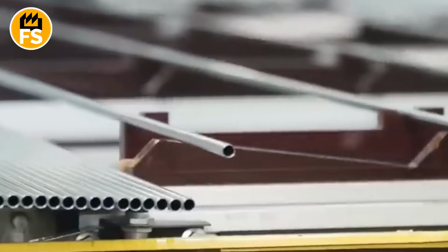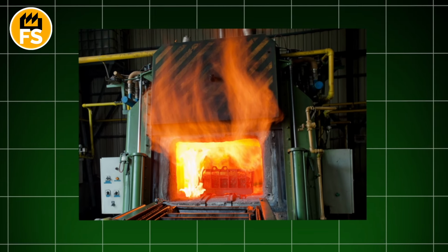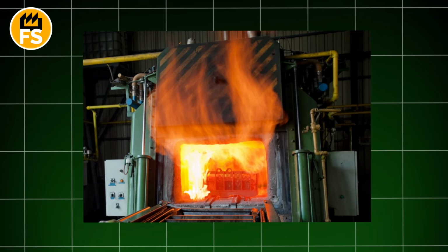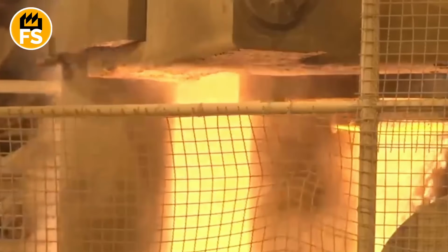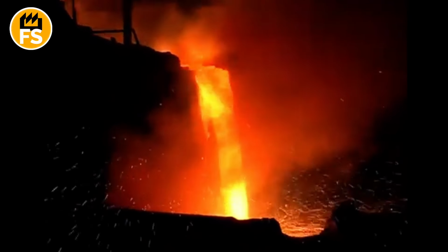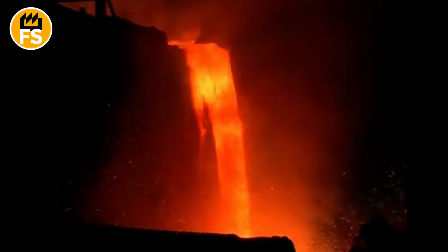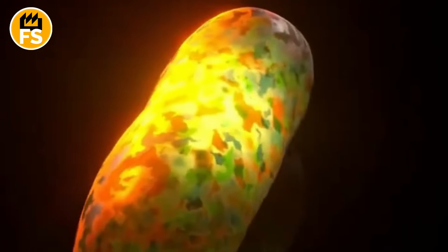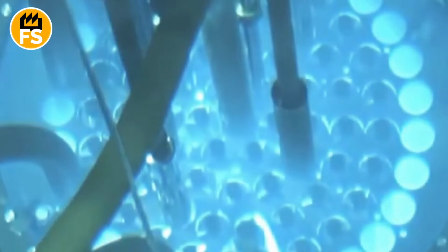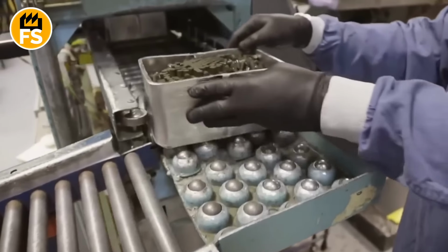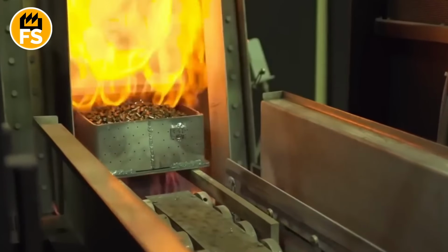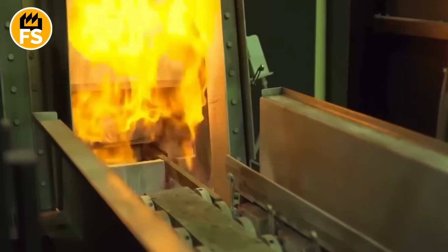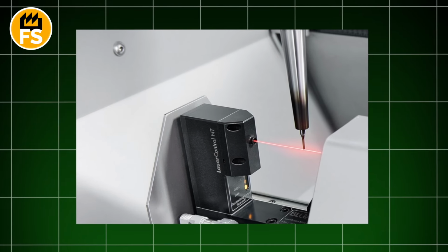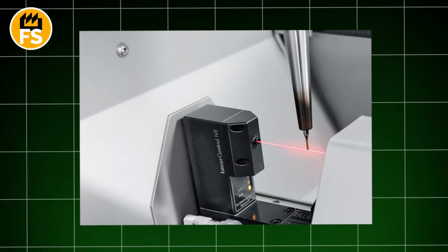But this is not an ordinary furnace. This is a high-temperature furnace, filled with hydrogen to prevent oxidation. There, at a temperature of over 3,000 degrees Fahrenheit, these pellets are baked for many hours. During this process, called sintering, the powder particles fuse together, and the pellet turns into an extremely hard, dense, ceramic-like substance. It becomes so strong that it can withstand the extreme temperatures and pressures inside a nuclear reactor. Each pellet after this undergoes laser control, which checks its dimensions with micron accuracy.